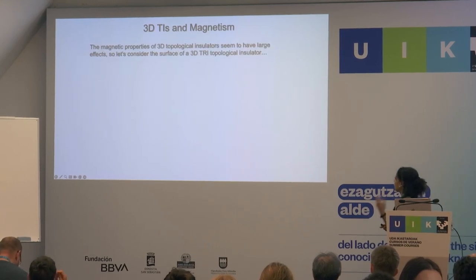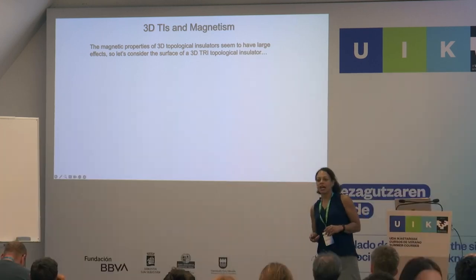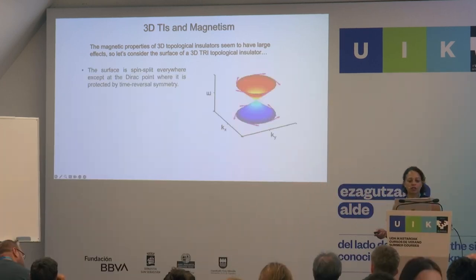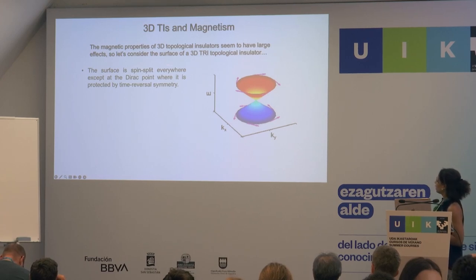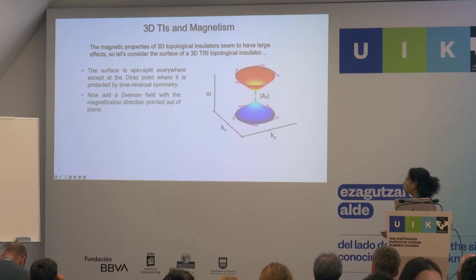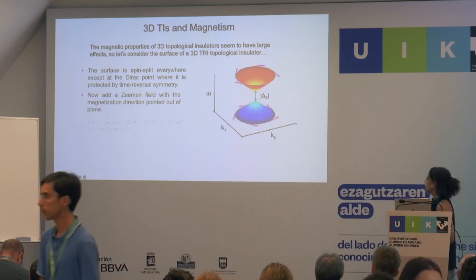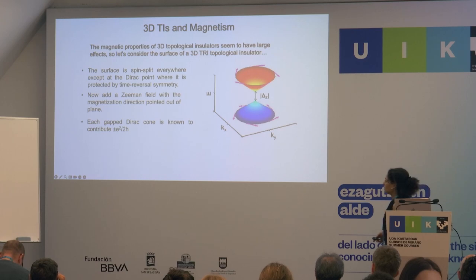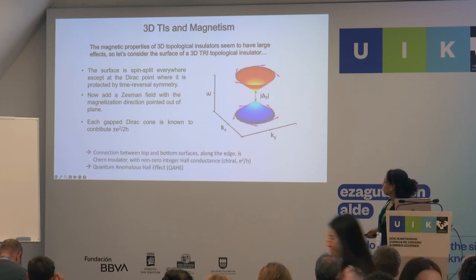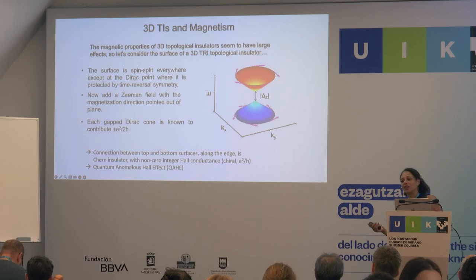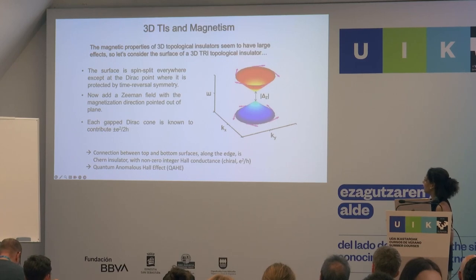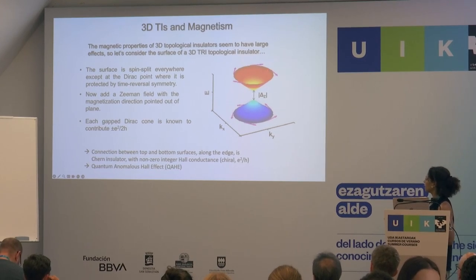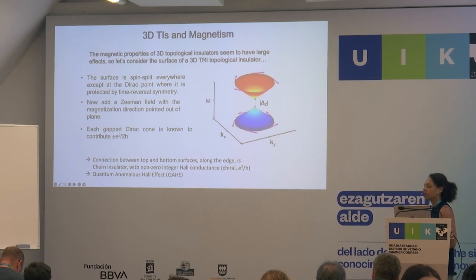And so, as I mentioned, if you just consider what happens to a topological insulator when you add a magnetic field, you start with this spin split surface, which is spin split everywhere except at the Dirac point, protected by time reversal symmetry. You add a magnetic field, and you create a gap in the states. Each gapped Dirac cone contributes e squared over h to the conductance. And then what people have studied a lot and what you've seen already is this is how you can get things like quantum anomalous Hall effect when you have magnetic doping in these materials. If you're connecting between these two states, you end up with a chiral state along the edges.